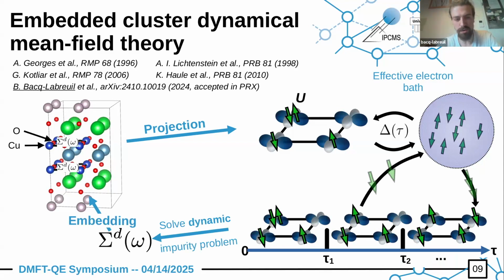And similarly as what you would do in DMFT in the Hubbard model, here you would embed, so put back the self-energy on the copper, so you would embed it into the Kohn-Sham basis, which will modify the rest of the degrees of freedom because you would need to recompute the charge density of the system, and then you would loop again, do the projection. Your bath will be modified, so you can solve a new impurity problem, get a new self-energy, and loop all around until you converge both the charge density and the self-energy.